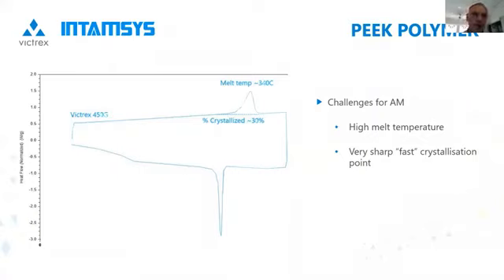So the additive manufacturing process obviously is very different, with longer residence times and in some processes hours or even days. And depending on the process, there can be localized areas of melt interacting with solid materials. The print builds up. And the build chamber is usually in an air environment where the bulk material can be held at temperatures just below melt for long periods of time.